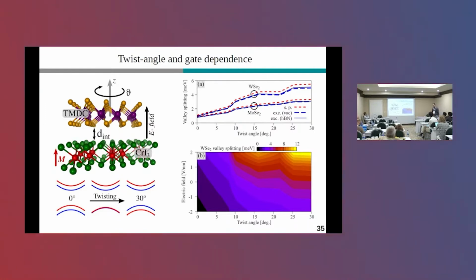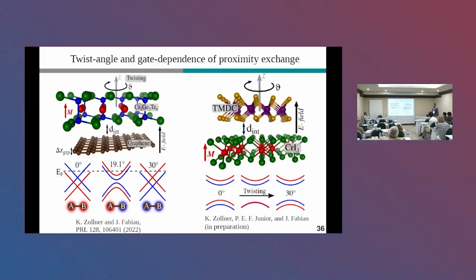And the tunability is really giant. You can go from 0 to 12 millielectron volts in the valley splitting by twisting and gating. These 12 millielectron volts correspond to an external magnetic field of 60 Tesla. And this is really a gigantic field. And this already brings me to the end of my talk. I hope that I could convince you that twisting and gating are two very efficient control knobs to tailor proximity physics into material heterostructures. And with that, I thank you for your attention.